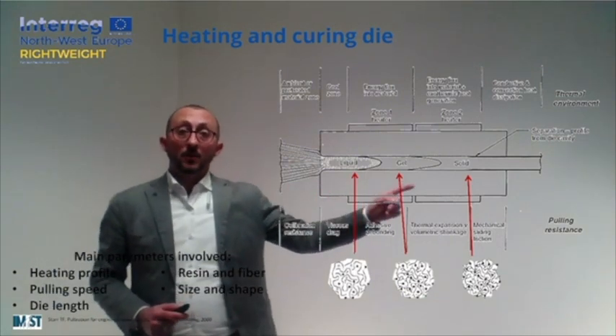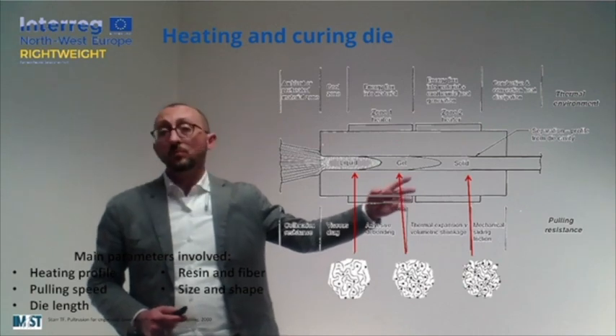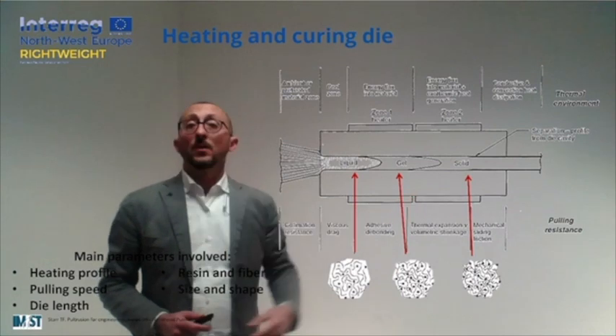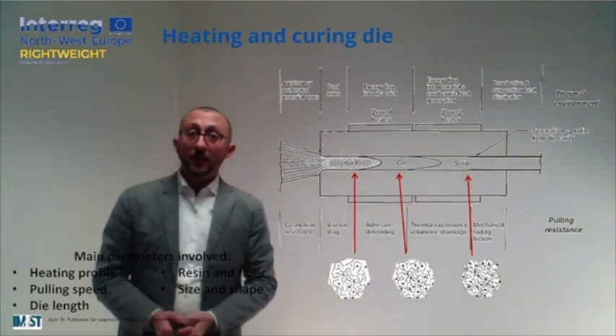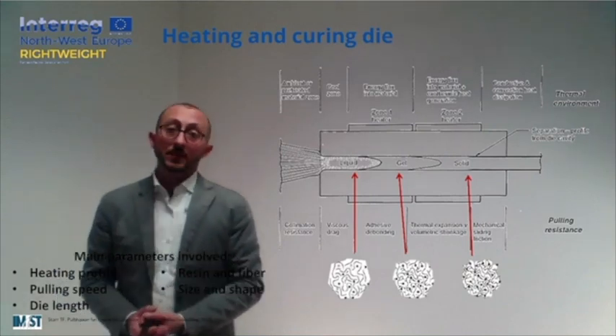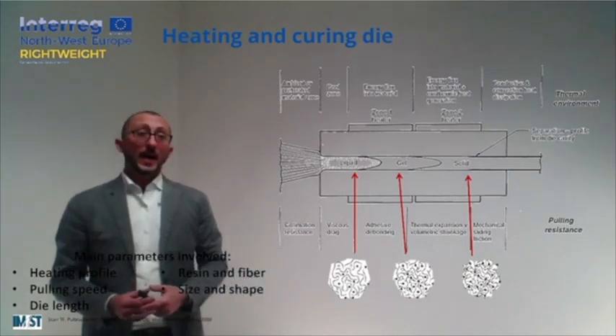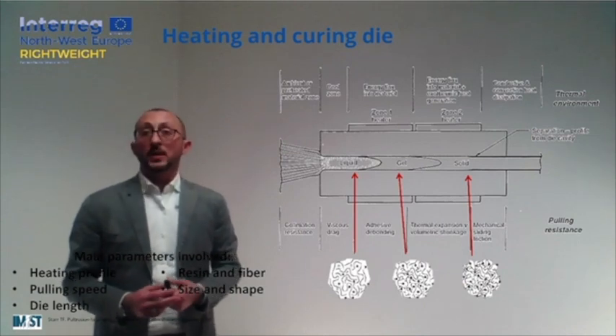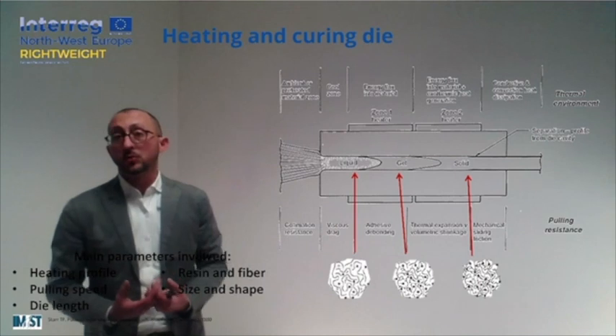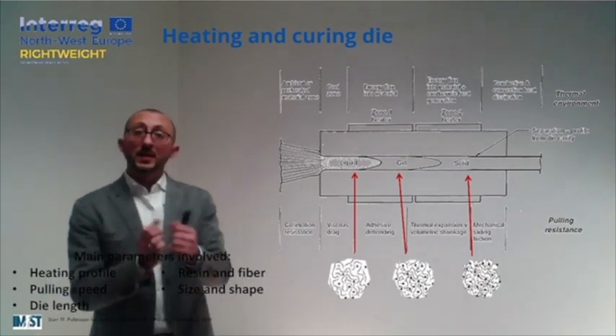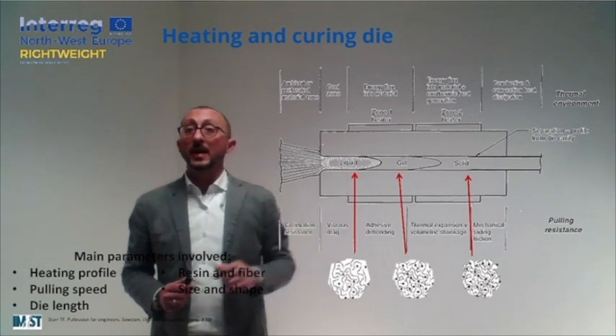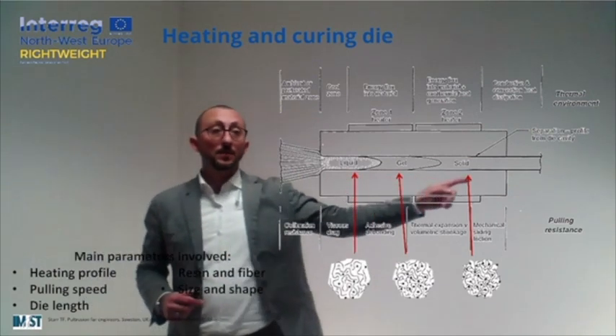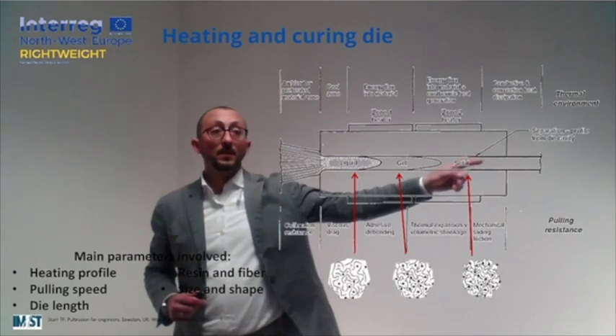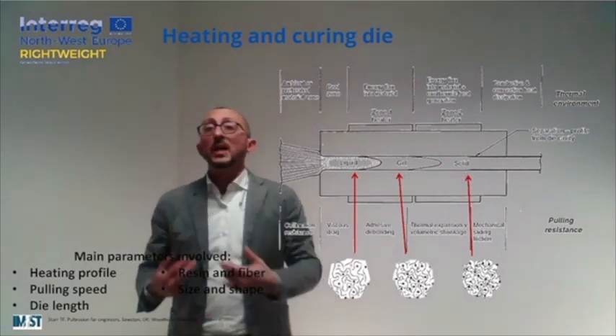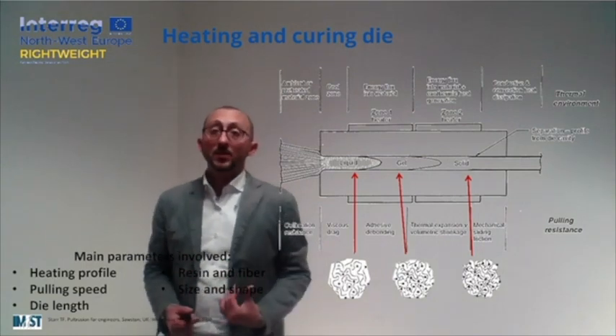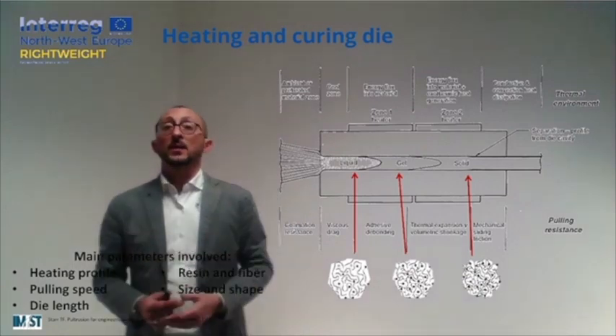And after a while, also the transition from the rubbery state to the solid state will be promoted. At that point, our pultruded workpiece is completely solidified, and due to the chemical shrinkage that is a common feature of thermoset resins, also some detachment of our workpiece from the die will happen, meaning that after this point here, we will not have any more interactions between the composite material and our die.